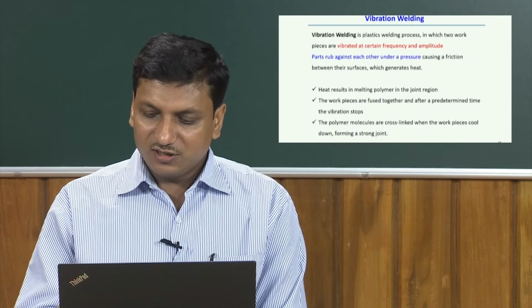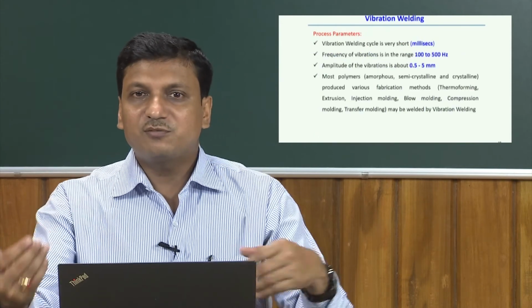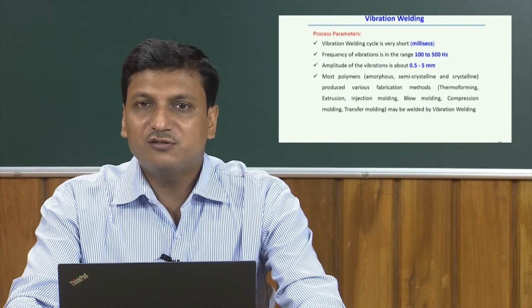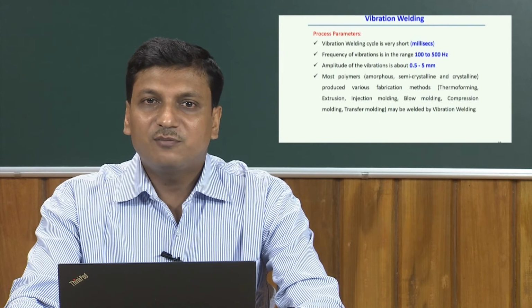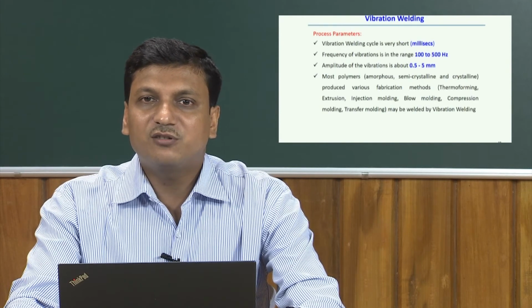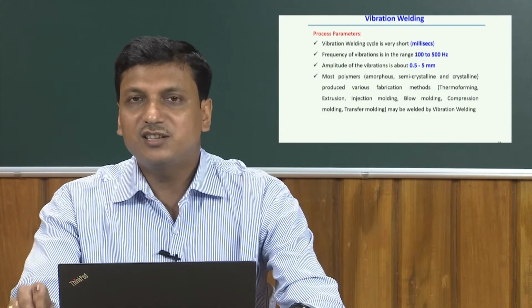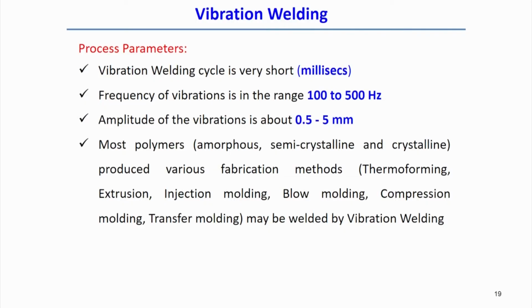We can see the typical process parameters in the vibration welding process. Here the vibration welding cycle is very short, even in milliseconds. The frequency of vibration is in the range of 100 to 500 Hertz, but in the case of the ultrasonic welding process, the frequency of the vibration was on the order of kilohertz.